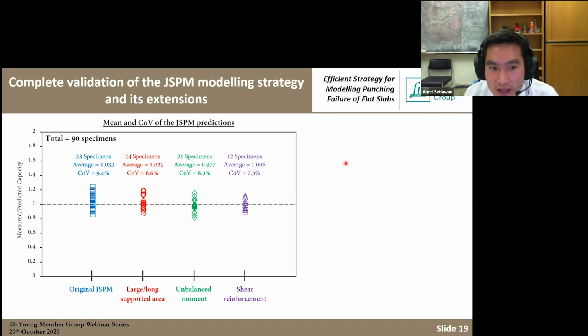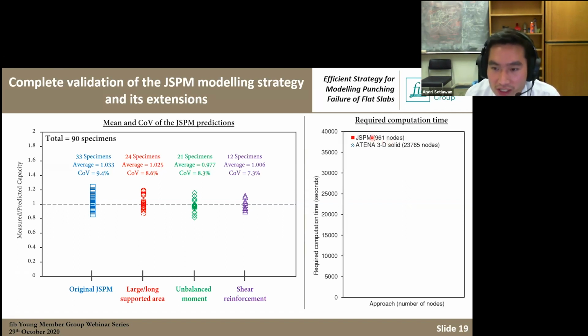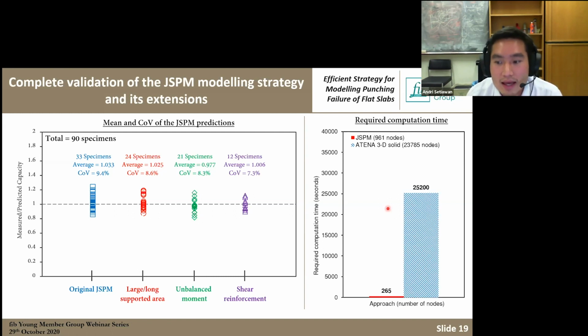And most importantly, we are also comparing the required computation time that we had for the same slabs between our model and also the 3D solid, just to make a distinct comparison. For the joint shell punching model, for a typical slab, we only have 961 nodes, whereas for the slabs where we model using the Athena 3D solid, we ended up with 23,785 nodes. And this is the required computation time, 265 seconds, which is basically like 4 minutes or something like that. Yes, and Athena solid, of course, has more nodes and degrees of freedom, so it takes almost 100 times longer to finish the simulation.